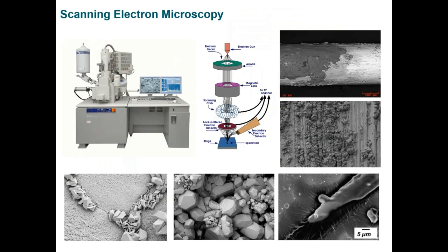Now, another key tool is microscopy. Scanning electron microscopy is a good way to look at the morphology in the presence of corrodant, corroding species, or the mechanism of corrosion. One can go to high-resolution SEM. Essentially, a conducting material like steel need not be sputtered, but this allows you, for example, to combine it with EDX and other types of elemental measurements that can characterize the corrodant species or changes in the metallic structure. So a very, very useful tool.